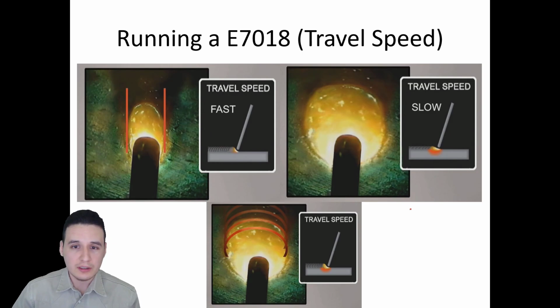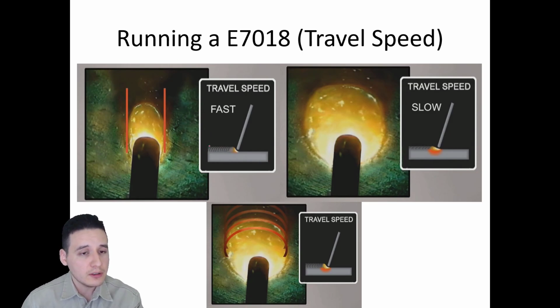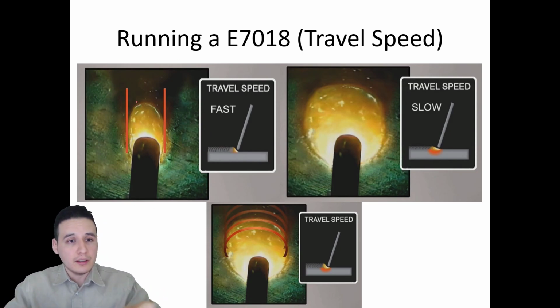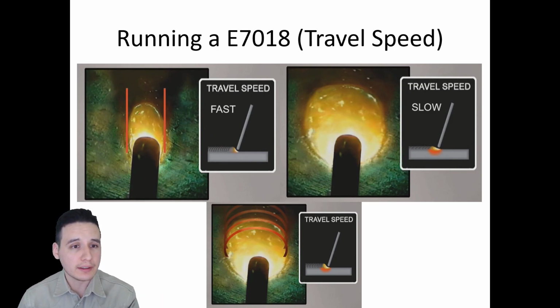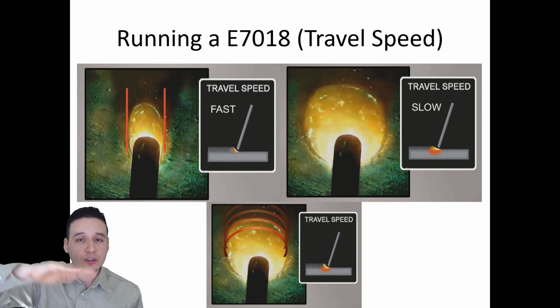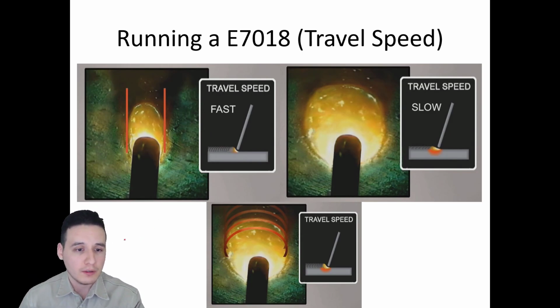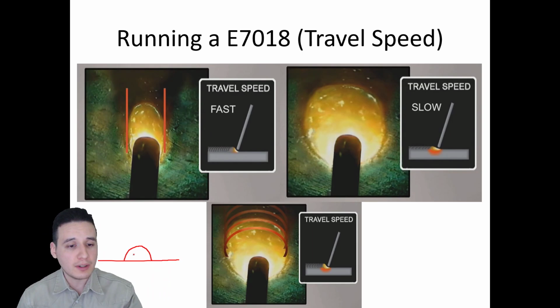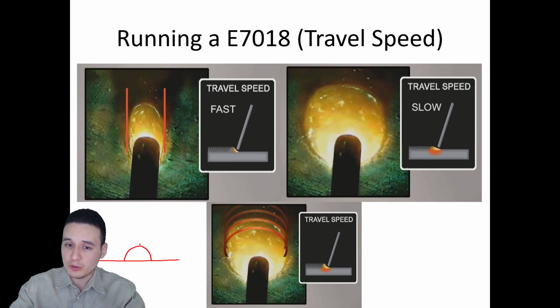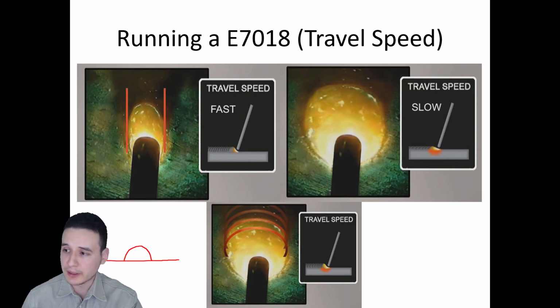If you move too fast, of course your puddle is going to start shrinking, and it'll look a little more like this. And notice, not only does it start shrinking, it becomes elongated. And remember, anytime we have an elongated puddle like this, that's going to cause our bead to crown up down the center quite a bit. For example, if we're drawing our bevel plate there, and that bead is crowned up like this, is that a smooth transition from our base metal to our weld? No, right? We need this bead not to crown up so high. We need it to flatten down. So you don't want to go too fast. You want to go, again, somewhere in between. So always keep that in mind.